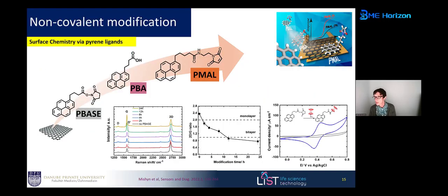Now I want to show you what will happen if we don't do diazonium chemistry, but use non-covalent modification. What you see here is that we tried for a long time to see what would be the best pi-pi stacking interaction chemistry on this type of graphene. So we compared PBASE with the acid form and with the pyrene-maleimide form. And we followed again over time the intensity ratio in the Raman. What you see here, using simple PBASE, is that when you leave it over a long time, we change from a monolayer to bilayers.